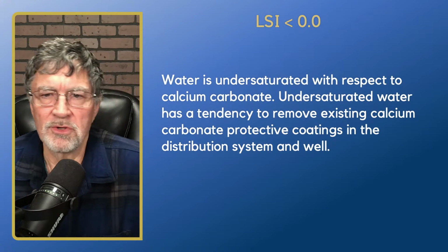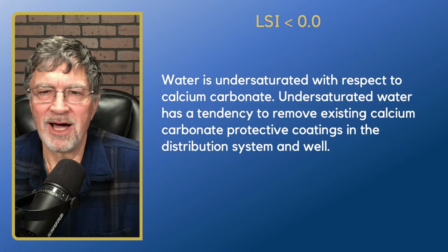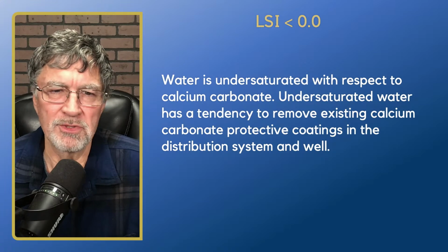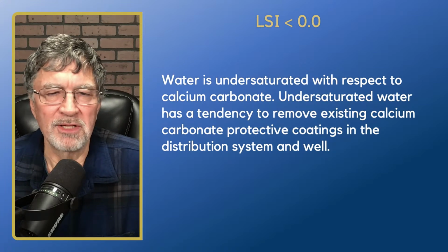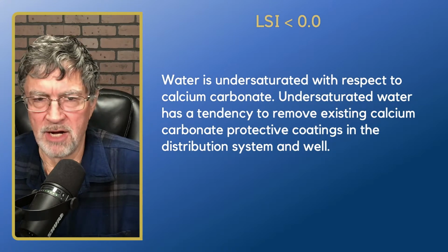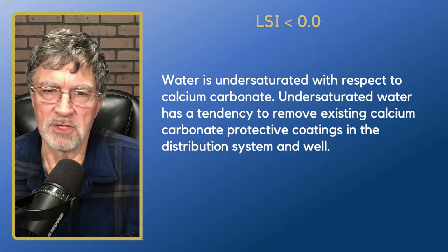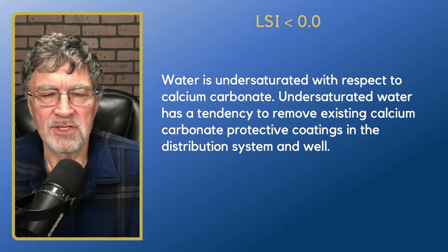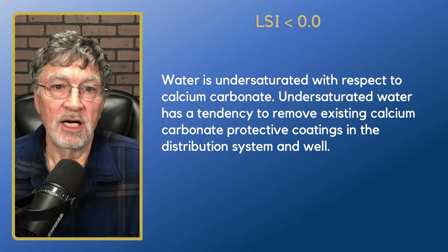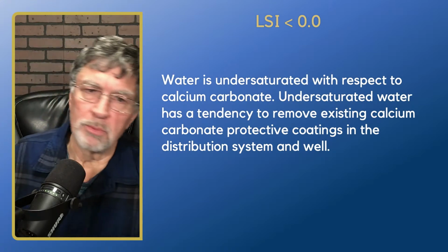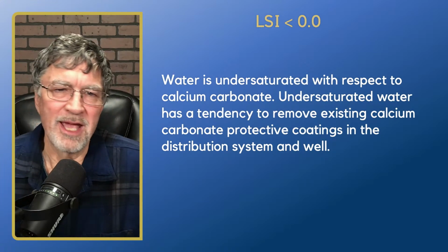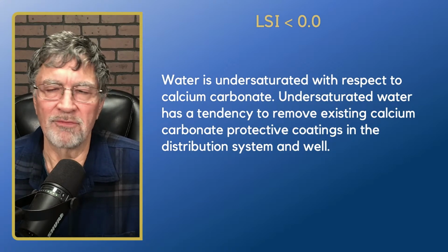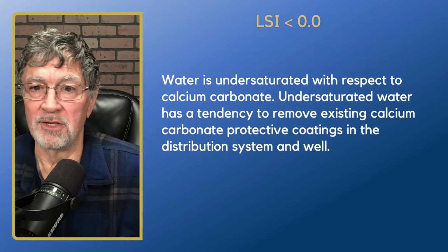Okay, so if the LSI is 0, the water is not undersaturated with respect to calcium carbonate, but it's just at the saturation point. Environments can vary in the well. The pump is on, the pump is off. So you're going to get some variability. If you're just at the saturation level, you might still have the potential for scaling with calcium carbonate because it can flip around a little bit. And once again, this is a calculated index, so variations in the pH, the calcium content and so on can cause variations in your LSI.